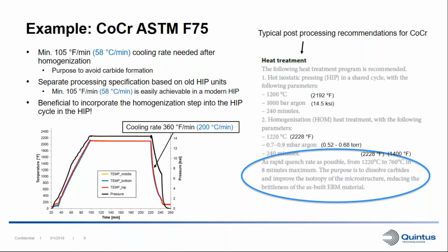This is very close temperature to the HIP temperature at 1200 degrees Celsius, and also a 4 hour soak time. And then in the homogenization step, it's specified a minimum cooling rate. The minimum cooling rate specified here corresponds to a minimum of 105 Fahrenheit per minute. And in a modern HIP system, we can easily achieve these kind of cooling rates. So it would make very much sense to combine these steps into one.